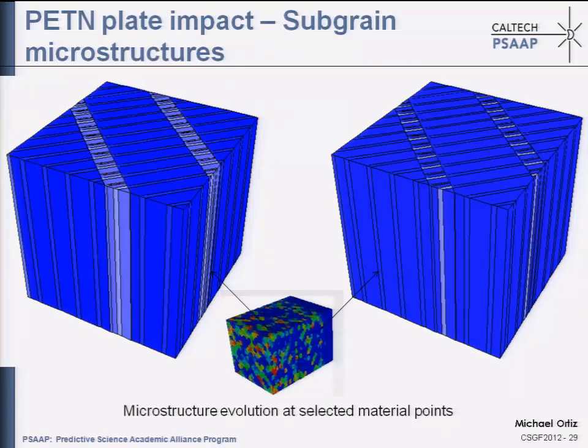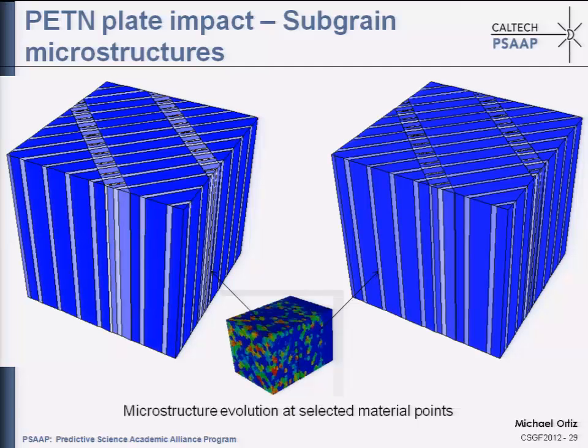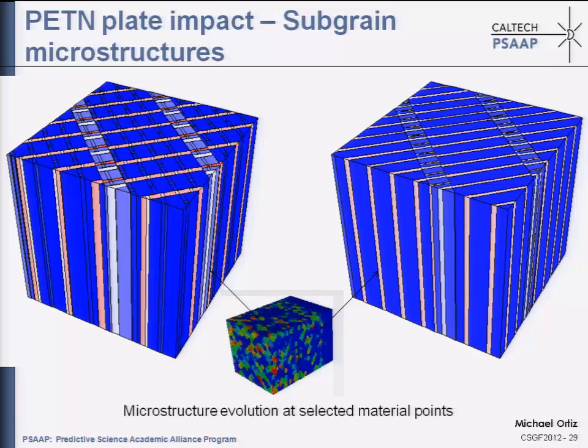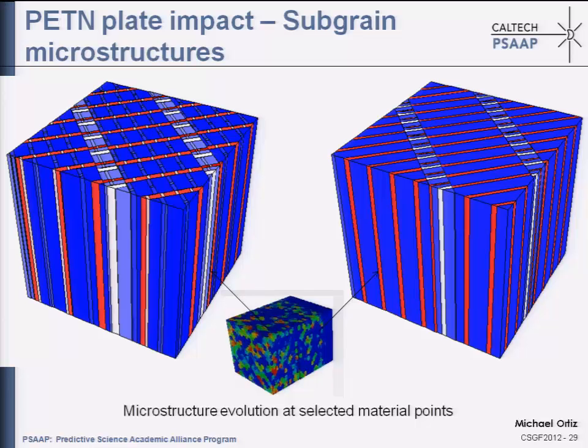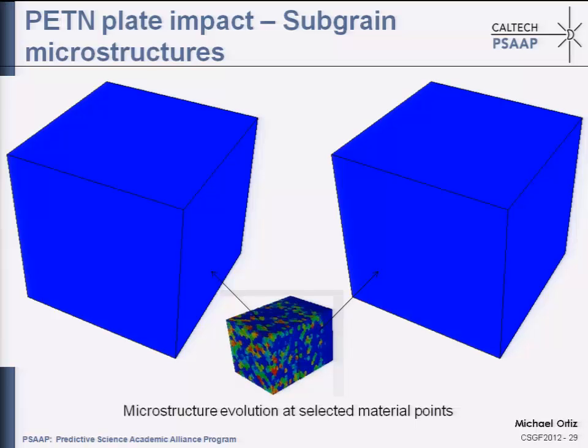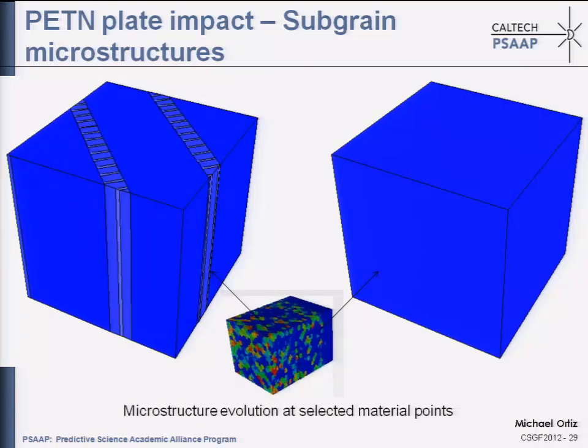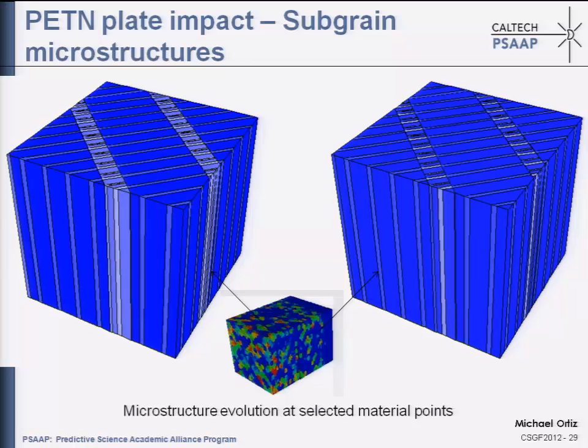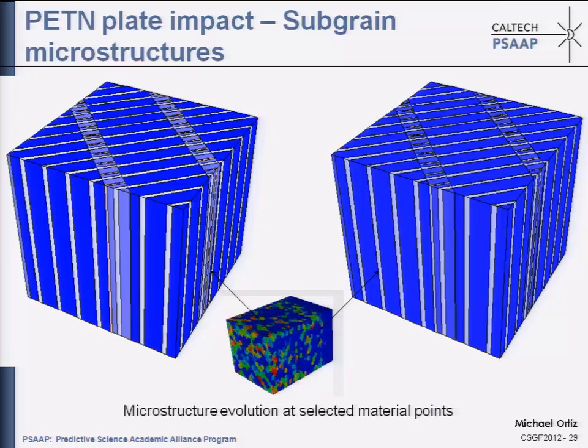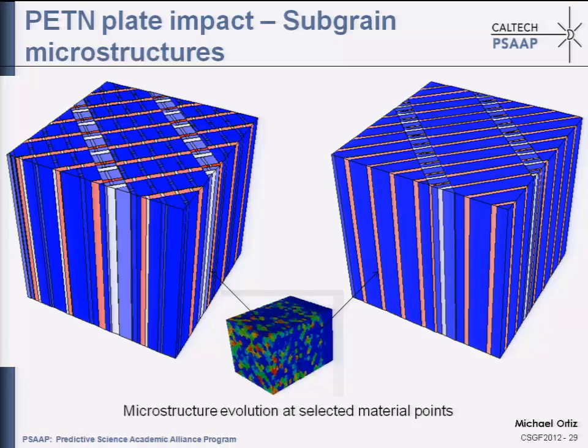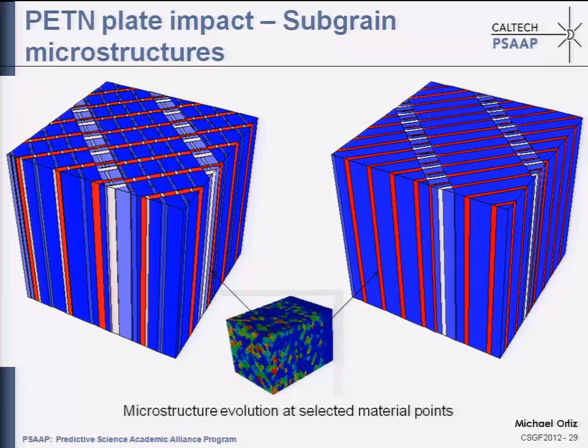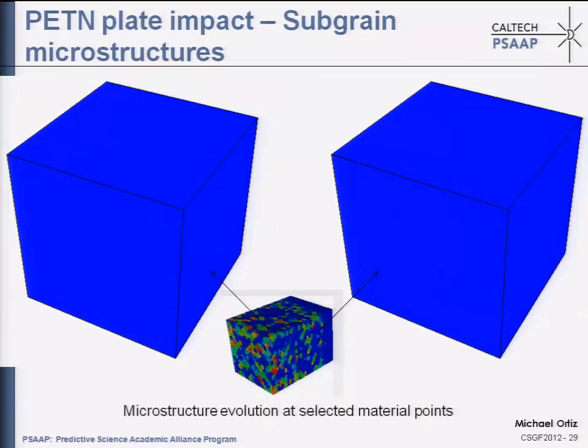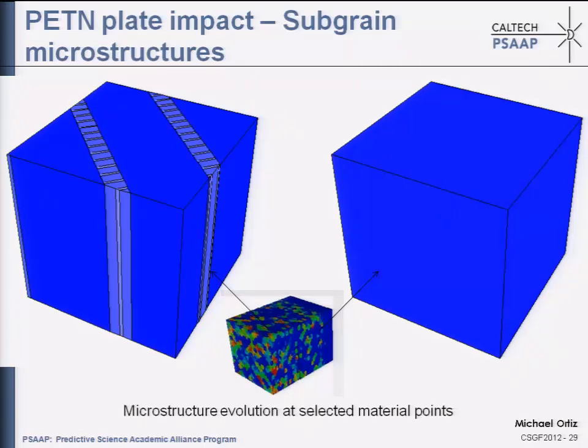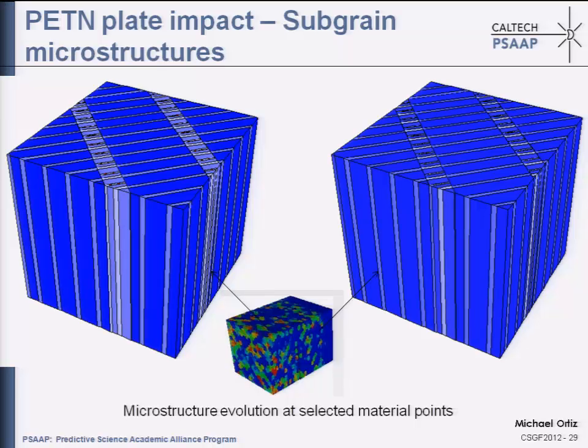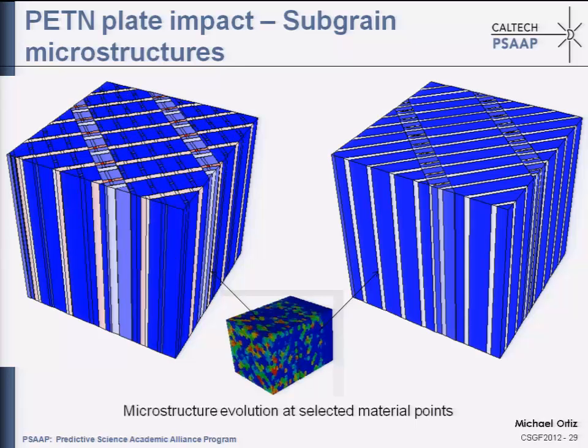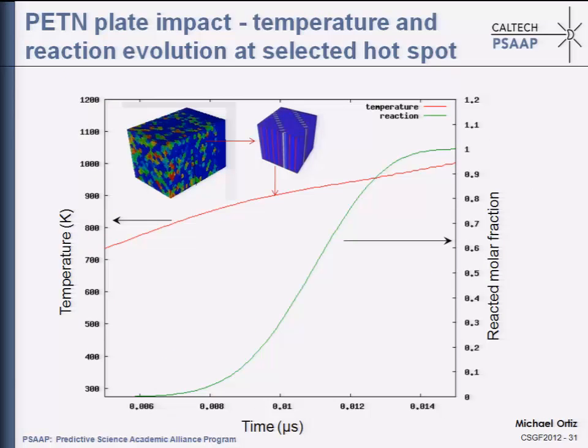And what I'm showing here is that I've taken two material points at random, and I'm showing the evolution of the microstructure, predicted by the microstructure model, at each one of those material points. Of course, there are thousands or perhaps millions of these material points, and this is just a sampler. And what you see is that at individual material points, you develop very fine microstructures where there are regions that are very highly deformed, that attain very high temperatures, and conditions that are, in fact, highly in excess of the macroscopic averages. So whereas the macroscopic average doesn't really give you any useful information regarding hot spots, the microstructural model gives you at least some handle or some information about, again, extreme values in the distribution of pressure, deformation, and temperature. And then you can collect some hot spot statistics, which is what I'm showing here.